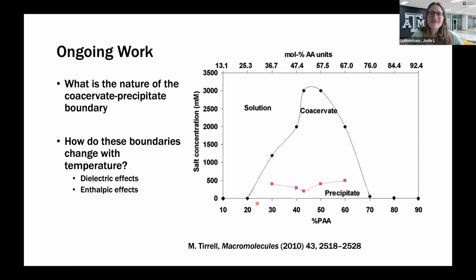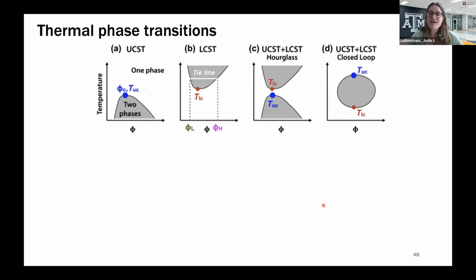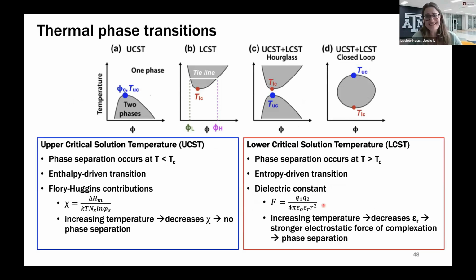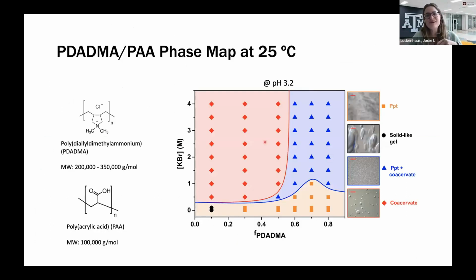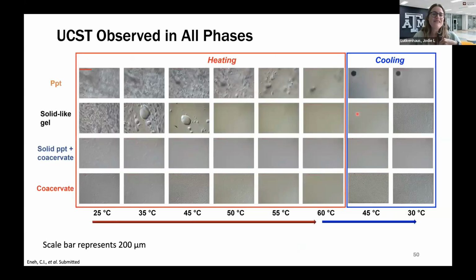So the last thing that's ongoing is we're trying to understand these phase boundaries. So I just want to show you these complexes can have UCSTs or LCSTs or both. And so we're trying to understand what drives that, whether it's entropic interactions with a Flory-Huggins interaction constant or dielectrics. And so in our unpublished work, we're now making phase maps of solutions, coacervates, precipitates, and how that relates. And so here's a picture of a liquid-like coacervate. It makes these beautiful droplets, these messy precipitates. And we can also induce these UCSTs in the system.